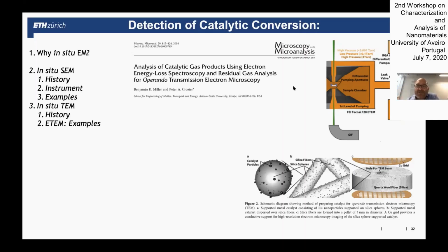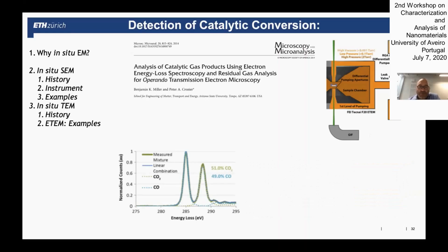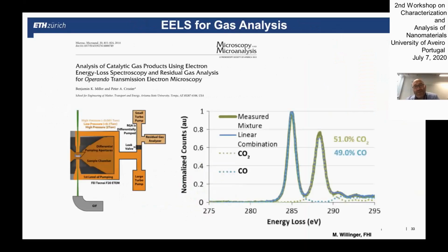And the cool thing here is that they use the electron beam not only for imaging, but because the electron beam has to pass through the gas phase, and when it shines through the hole, the electron beam interacts with the gas molecules. By analyzing the energy lost by the electrons when they interact with the gas phase, they can actually study the composition of the gas phase. And this is so beautiful when you look in the energy loss at how many electrons interact with carbon in the configuration of carbon monoxide or carbon dioxide. These electrons lose different amounts of energy, and they could really spectroscopically study how much CO conversion they had, CO oxidation to CO2, because the CO and the CO2 have different locations in the carbon K edge feature. So this is a beautiful example.